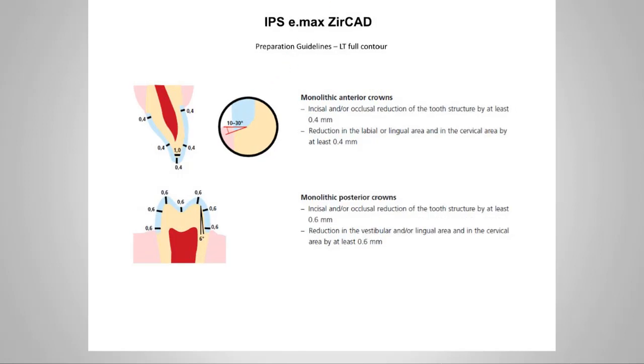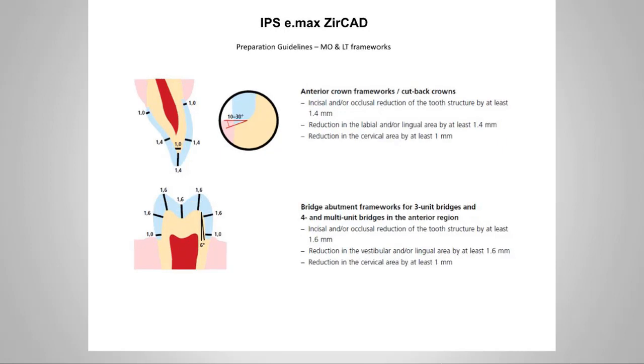If you're using the LT full contour, this shows that for the anterior, you can go as thin as 0.4 of a millimeter, and that's quite thin. The posterior can go as thin as 0.6. Once again, you're looking at a chamfer margin.